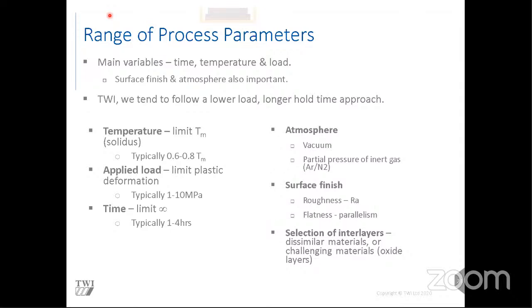The reason for that is the limitation of our furnace. As I've already explained, we have a 35 kilonewton maximum load, so that often limits the pressure we can apply, especially with a large surface area component. But if you work in a laboratory, you'll often be working on smaller coupons, which allows you to apply a much higher load and increase heating rates and reduce cooling times. But we tend to go for the lower load, longer hold time approach.